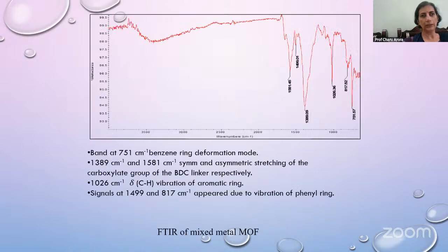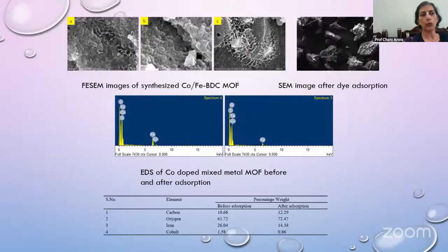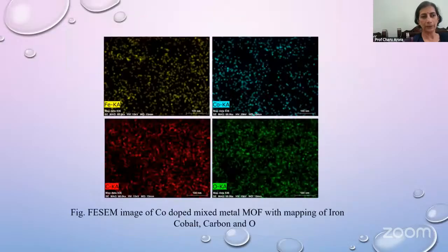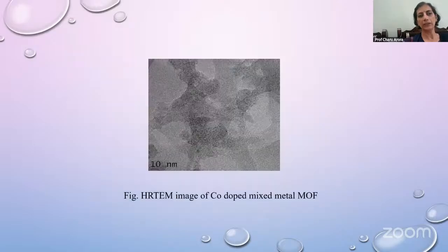These are the characterization results: IR and XRD of the doped MOF, and we have recorded SEM-EDS, which indicated that doping of cobalt has successfully taken place. These are the FE-SEM images showing that cobalt has been doped successfully. This is the TEM image.